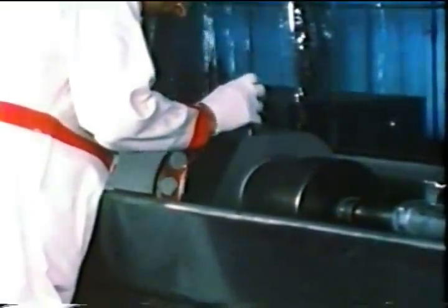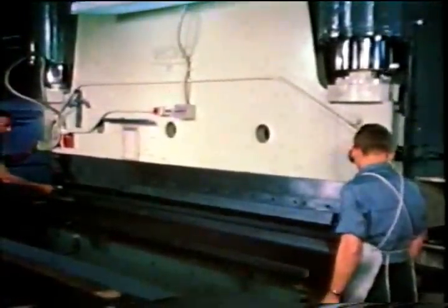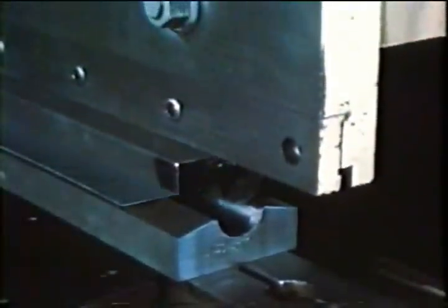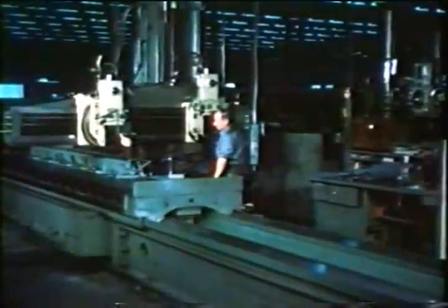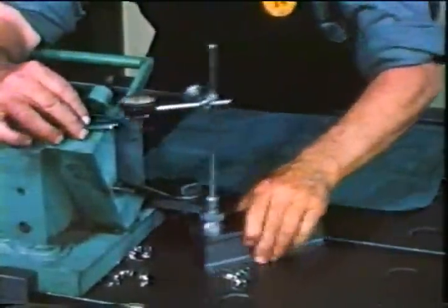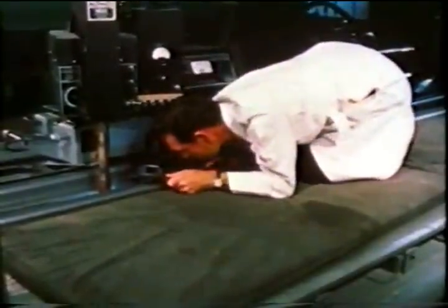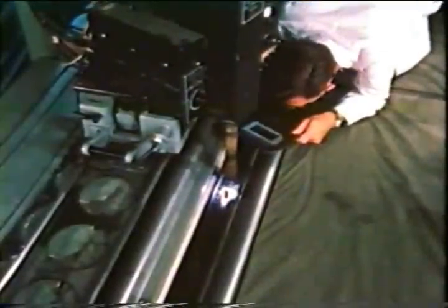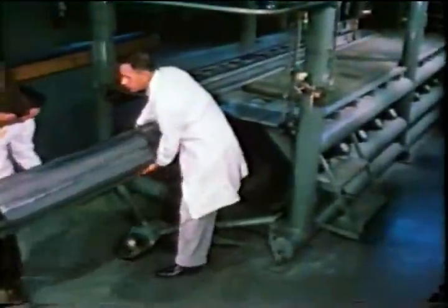Among the most unique fabrication techniques were those associated with the moderator assemblies. Reactor-grade graphite was machined into a hexagonal shape before being sealed in zirconium cans. The moderator cans were fabricated from 6 separate longitudinal panels of zirconium. The formed panels were machined to the specified width. A heliarc welding stake was used for the longitudinal welding. The seams were fused together without filler rod to assure a minimum of contamination.